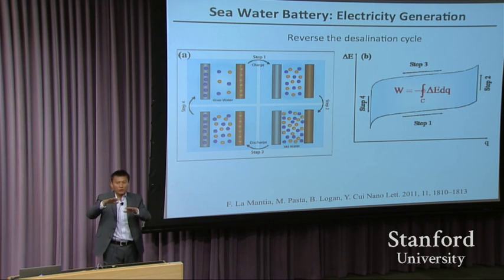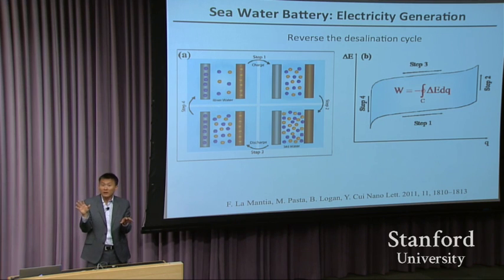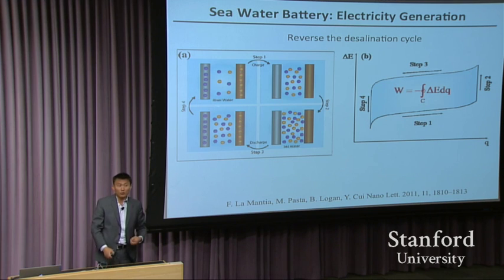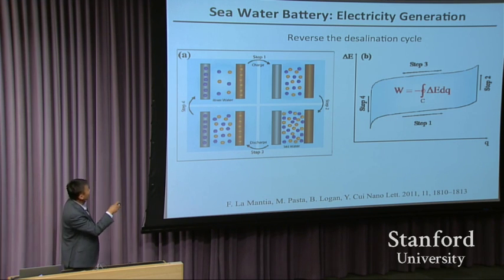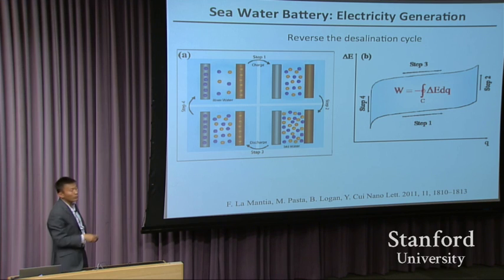100 times difference, this is your thermodynamic energy, your entropy energy. If you take the log of 100 times, for sodium ion alone, that generates about 120 millivolts of voltage difference if you use that as electrolyte for the battery. And chlorine generates another 120. Adding together, it's 240 millivolts of voltage difference. That's the energy you can take out. So if you reverse the cycle, now you are seeing this. You have the same thing, sodium manganese oxide and silver chloride. You have river water. There's not much salt in there.